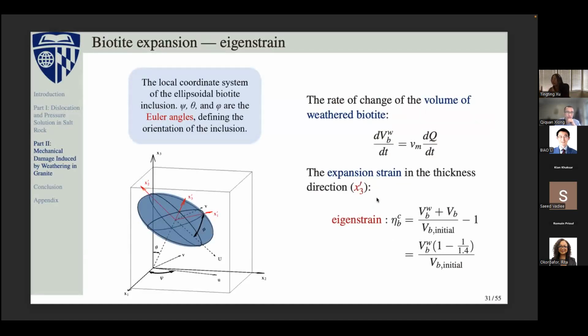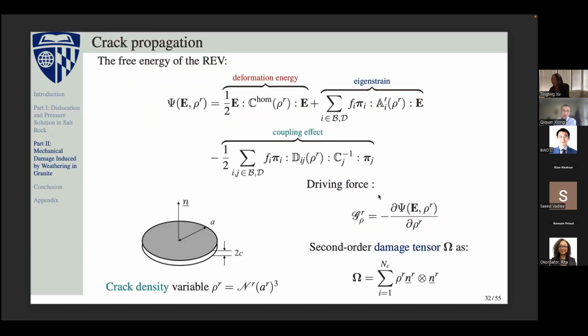So for the first mechanism, it is the biotite expansion, as I just said, and we have the eigenstrain or the misfit strain. Here I provide the exact formulation for this eigenstrain, and this eigenstrain is really dependent on the volume change of the biotite to other minerals. So that is a local behavior for the biotite inclusion. And on top of that, we give the thermodynamic-based model for this whole REV to consider the combination of the biotite weathering and also the crack propagation.